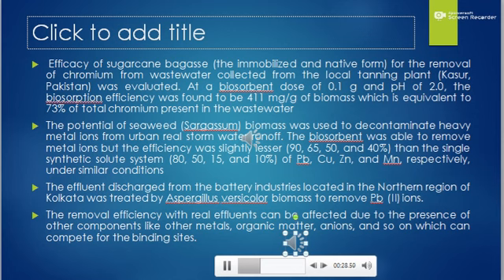In another research, the potential of seaweed used as a biosorbent was studied to decontaminate heavy metal ions from real urban storm water runoff. The biosorbent was able to remove metal ions, but the efficiency was slightly lower than in a single synthetic solute system under similar conditions.